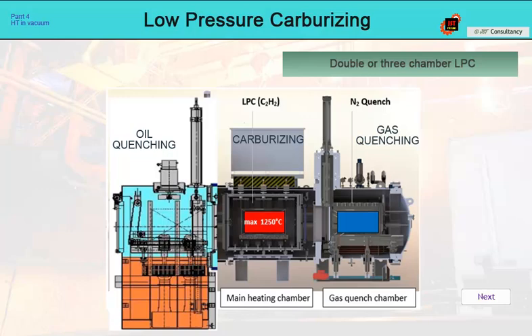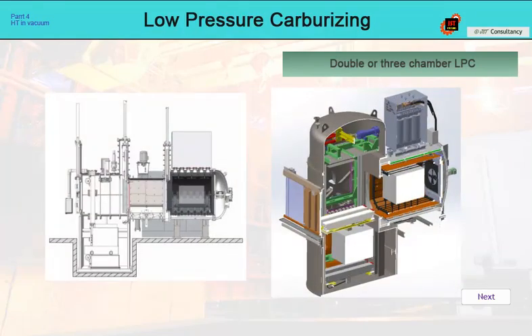However, since multi-purpose furnaces are also used for other types of processing than carburizing, to be able to carry out these processes, we need additional furnace equipment. For example, to be able to carry out normalizing, the oil quenching chamber should be equipped with a cooling fan and the possibility of nitrogen cooling up to 1 bar absolute pressure. The same applies to various annealing processes.